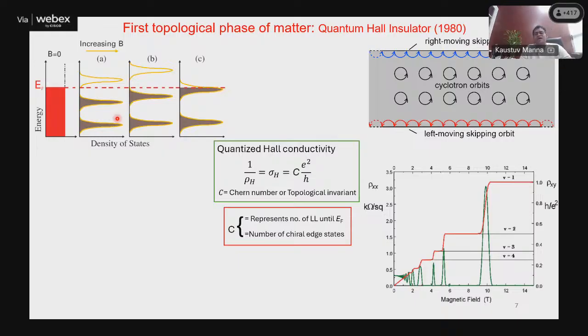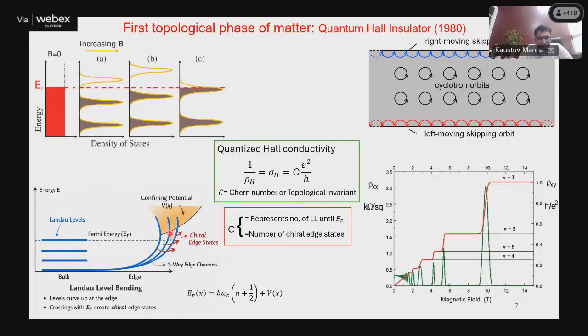So for that, we have to go to another picture, which is the bending of the Landau levels. This is the full picture; whatever I showed earlier is what is happening within the material. But when you go from inside the material to outside the material, there is a crossover, which is the edge of the material. Beyond the edge of the material, the potential is infinite. So the electrons which are already inside the material, unless you overcome that barrier, the infinite potential, or let's say the work function, you cannot take that carrier outside the material.